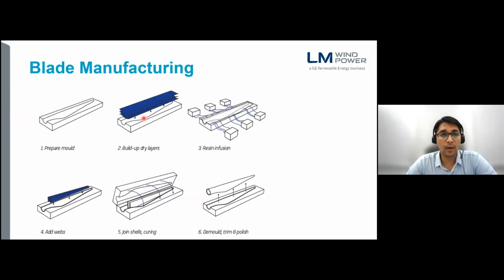Quickly moving to blade manufacturing, you might probably know that all the composite material parts that are longer than about 1.5 to 3 meters would be produced by a very standard process called vacuum assisted resin infusion process. And specifically for a wind turbine blade, we have two of these processes established. So we have one mold for the downwind, so one half shell of the mold, and the other mold for upwind. And what we do is we prepare the mold by applying release agent and all the necessary preparation.